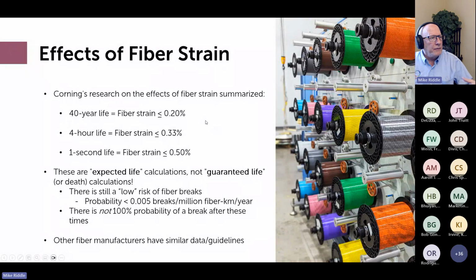If you go dig out the Corning paper where you find this, it says fiber stress less than or equal to 0.2% of the proof test, and the proof test is 100 kpsi. So that makes the conversion very easy. If you use 200 kpsi fiber, yes, you would have different values. But 99.9999% of the fiber being processed today by cable manufacturers for general use is the 100 kpsi fiber.